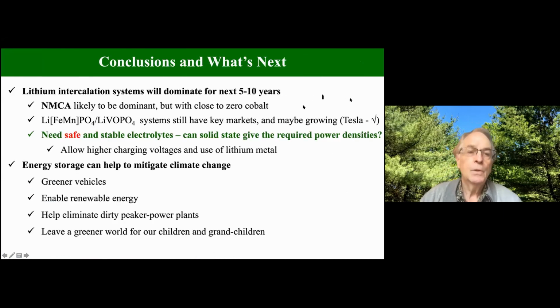So let me conclude with a few comments. It's my belief that lithium intercalation systems will dominate for the next 5 to 10 years. NMCA will be the dominant phase for grid and vehicles. It will go to close to 0 cobalt, if not to 0 cobalt. The phosphate systems will have key markets, and these are probably growing, particularly with Tesla now promoting it for their long-range vehicles. The real limitation, besides the graphitic carbon anode, is that we need a safe and stable electrolyte.